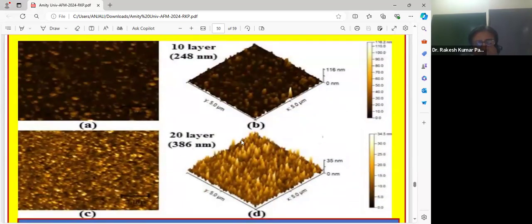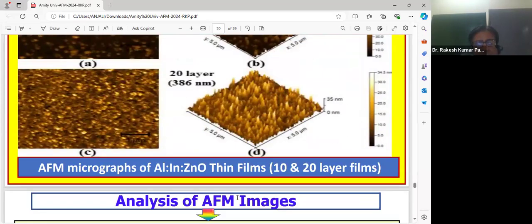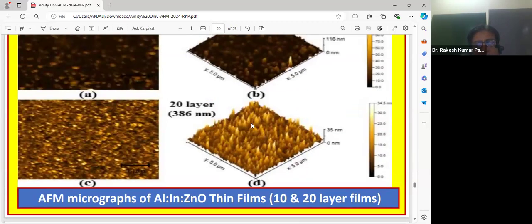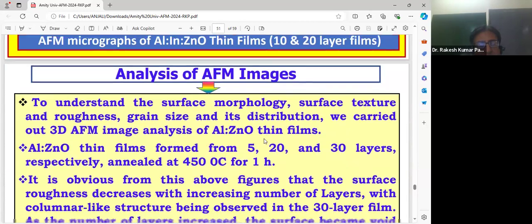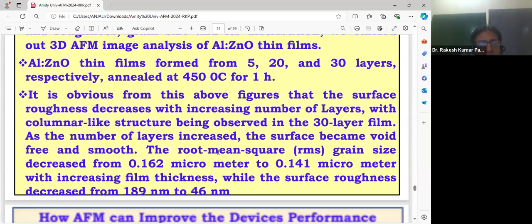This is another 2D and 3D image of aluminum and indium. Here, to change the characteristics, especially the energy band gap of zinc oxide thin film, along with aluminum we have added indium. So this is the aluminum and indium doped zinc oxide thin film, and the thickness is 10 and 20 layers. See how, as you increase the thickness, the roughness is improved.